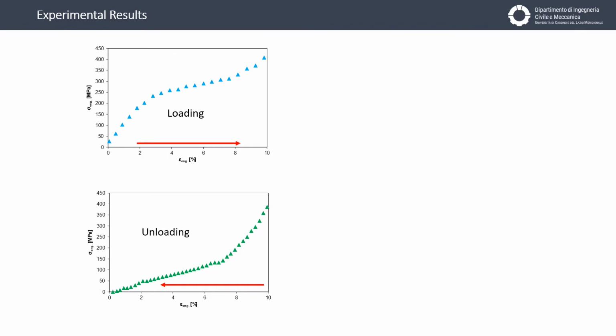Tests have been performed by using a loading-unloading cycle test, and here we can see the first cycle split in two different cases. The first one is the loading condition, with the first stage characterized by the presence of austenite. The second stage is the plateau, but you can see the plateau is not characterized by a slope equal to 0, but the slope is greater than 0. It's the minimum slope that you can see in these curves.